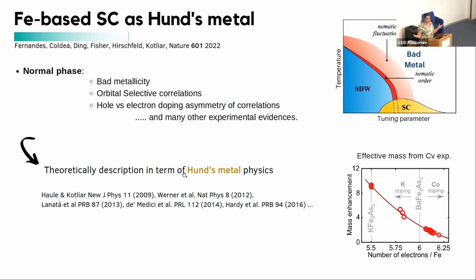There is agreement from experiment and theory, and I cannot enter in detail, just show you some, for example, fit in which, according to this theory, you will have a strong particle-hole asymmetry around the parent compound. For example, if you dope barium-122 with cobalt and potassium, you can achieve this experimentally and explore the phase diagram in that sense. And you see that the effective mass follows the fit perfectly. And this is quite peculiar of the Hund's metal physics. I don't think that is important. Just believe me, there is agreement that the normal state can be described by the Hund's metal.